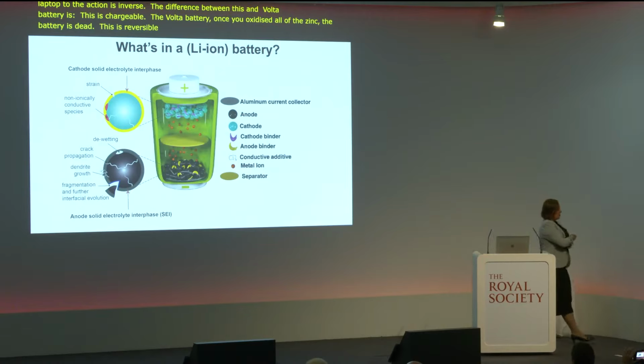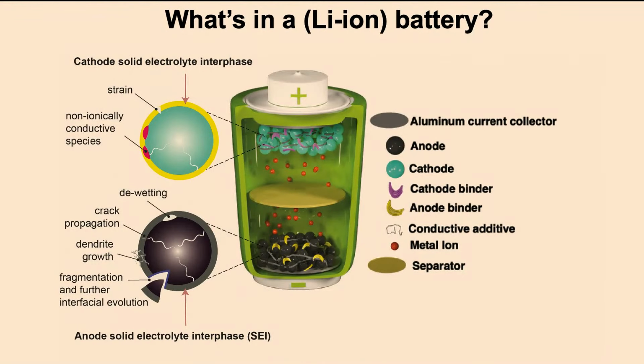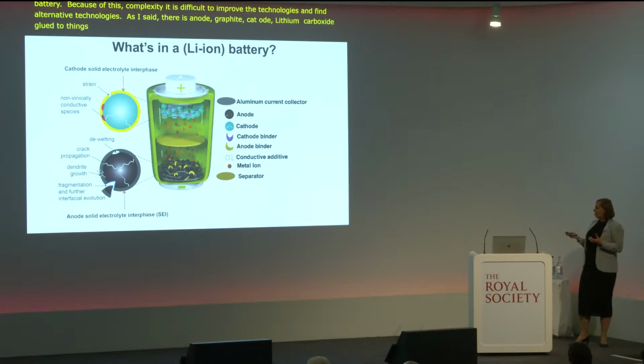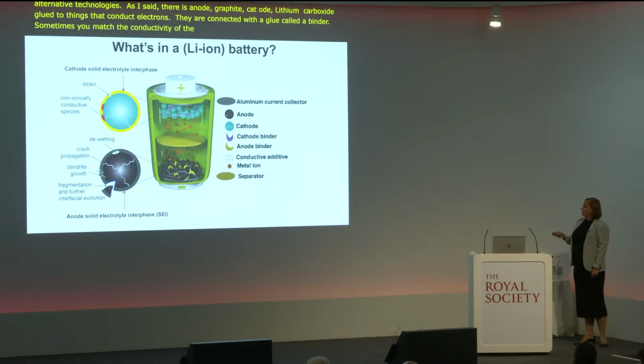Now, you may wonder what's in a lithium-ion battery. I said there's an anode and a cathode and an electrolyte, but actually things are very, very complicated. There's a lot of things in a battery. And because of this complexity, it's just so difficult to really improve these technologies and also find alternative technologies. So as I said, there is an anode, this is graphite, there is a cathode, let's say this is lithium cobalt oxide, and these are glued to current collectors, things that would conduct electrons. And the way they're glued is using a sort of glue, which is called a binder. Sometimes you add something else that is even more conductive to match the conductivity of these metal collectors and pass electrons through the anode and a cathode.